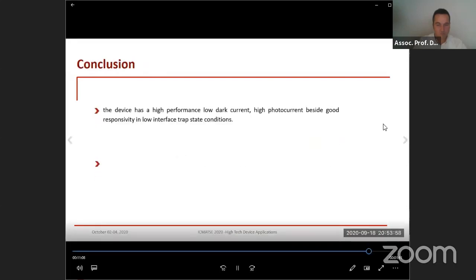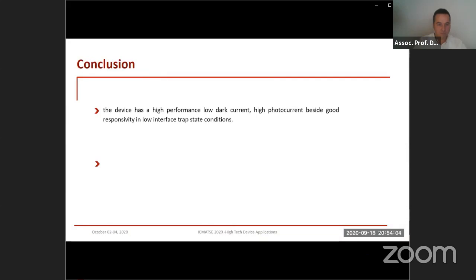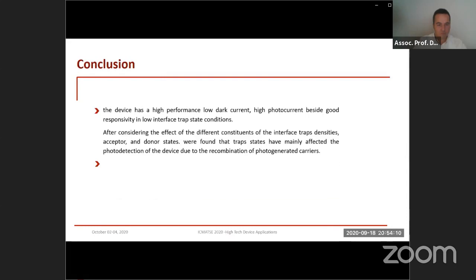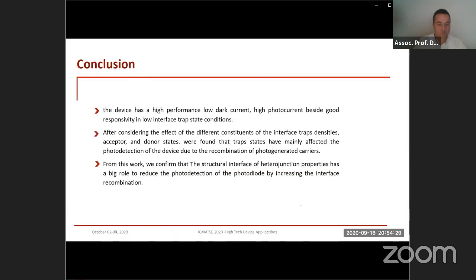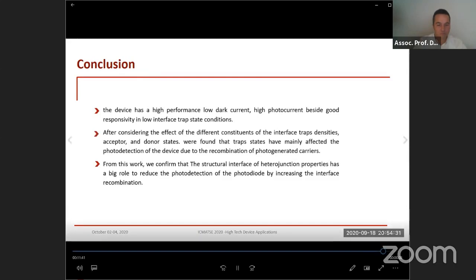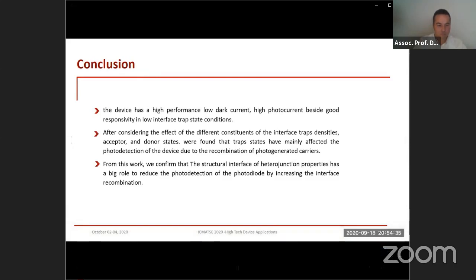We have talked about a device with high performance, low dark current, high photocurrent, and good responsivity, under low interface trap state conditions. After considering the effect of different constituents of the interface trap densities, acceptor and donor states, we found that trap states mainly affected the photodetection of the device due to the recombination of photogenerated carriers. From this work, we confirm that the structural interface of the heterojunction plays a big role in reducing the photodetection of the photodiode by increasing the interface recombination.